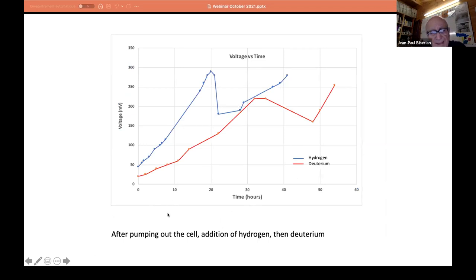Now, if I wait after pumping out the cell and I put in hydrogen, you have the curve with hydrogen and the curve with deuterium, and they are very similar in terms of time. The voltage goes up slowly. There are some variations here, but they are very much similar between hydrogen and deuterium. You cannot really compare them because I'm not sure it's very reproducible at this point yet. It has to be checked. Anyway, there is definitely an effect of voltage being built up there.